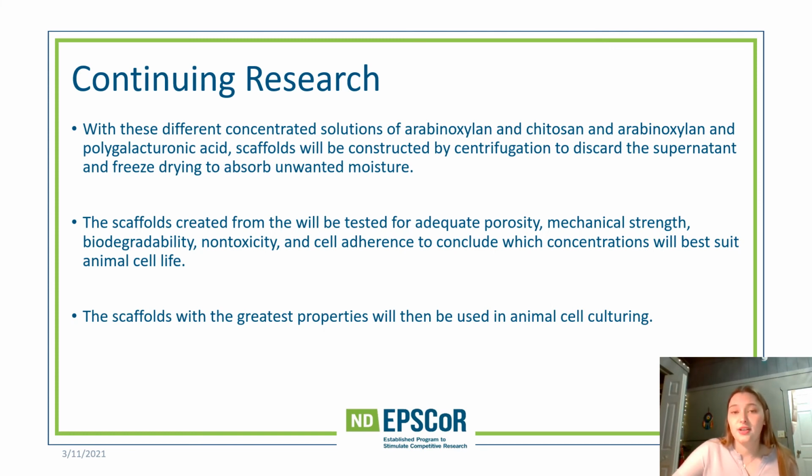Scaffolds will be constructed with the different concentrations of the made-up solutions talked about previously, by centrifugation to discard the supernatant and then freeze-dried to absorb more moisture. The scaffolds will then be tested for porosity, mechanical strength, biodegradability, non-toxicity, and cell adhesion to conclude which concentrations will best suit animal cell life, and then those scaffolds will be used in cell culturing.